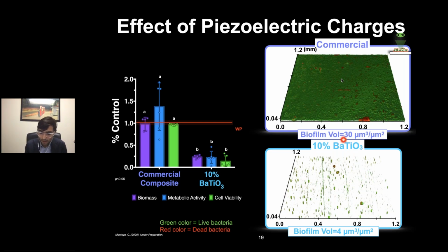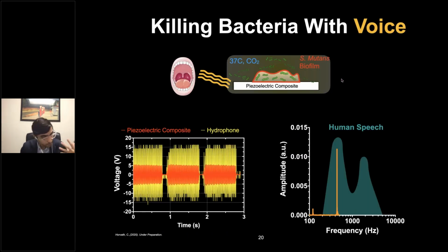So we went from having a volume of biofilm of 30 down to 4, right? So it's almost like 10 times less, which is a great decrease on the bacterial activity. Great results. For the first time, we showed that with the piezoelectric charges activated by the mastication forces, we were able to obtain antibacterial effects.